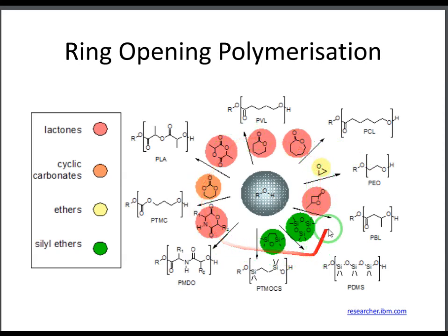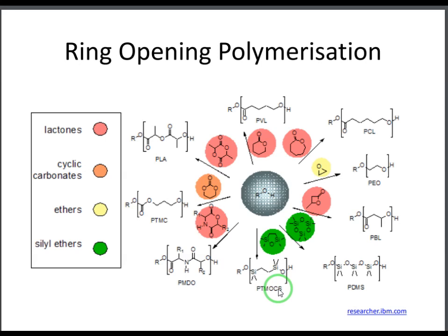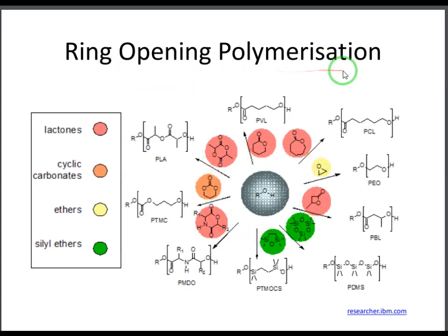We have different types of monomers in their ring forms that can easily react with an alcohol and be opened, then propagate to reach the final polymer. Note that if there is any water present in the solution it will affect the final quality of the polymers. Also remember that these ring monomers are only active once opened, so this method is a controlled polymerization — problems with termination and chain transfer do not seriously occur.